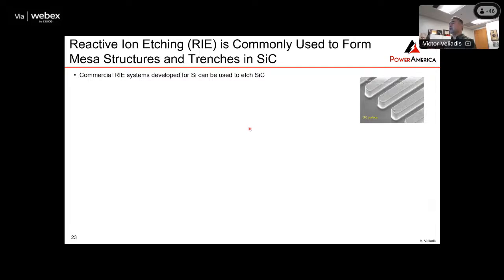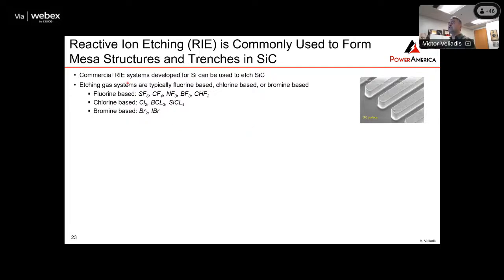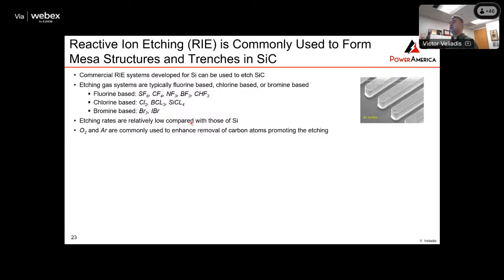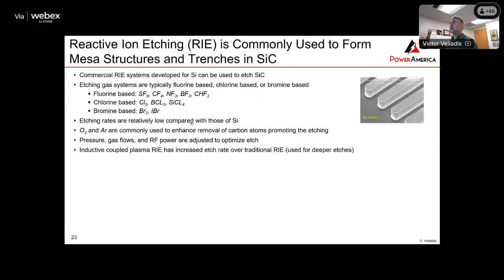There are commercial reactive ion etch systems that were developed for silicon, and they're fine to etch silicon carbide. There are different chemistries that can be used to do silicon carbide etch, with SF6 being a very popular one. The etching rates are relatively low because silicon carbide is a very hard material, so it's very difficult to etch it down. Oxygen and argon are used to enhance the removal of carbon atoms to promote the etching. You have to adjust the pressure, the gas flows, and the RF power. Inductively coupled plasma RIE can help you increase the etch rate, much like in silicon.